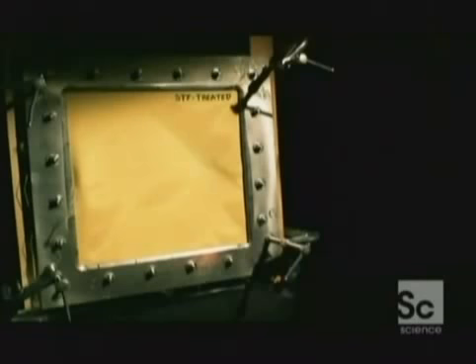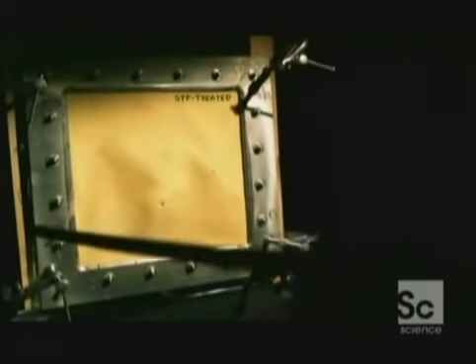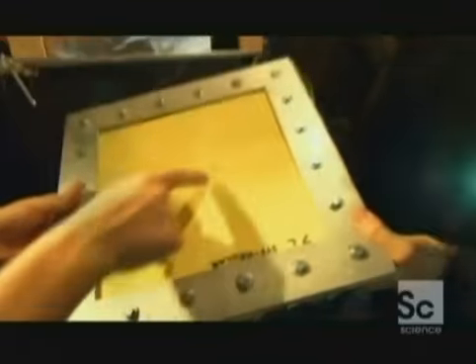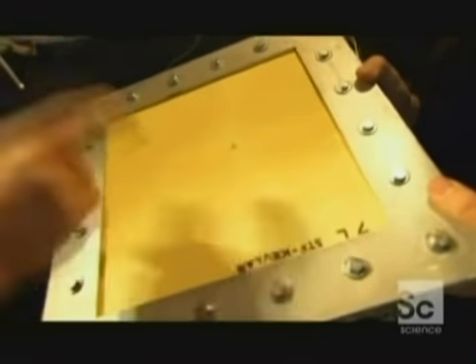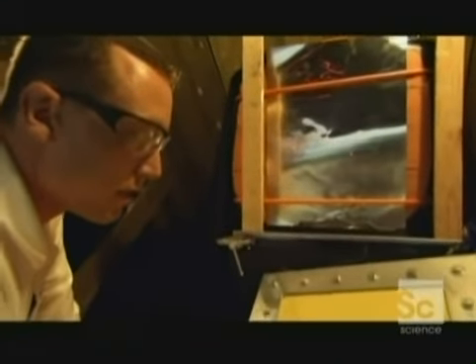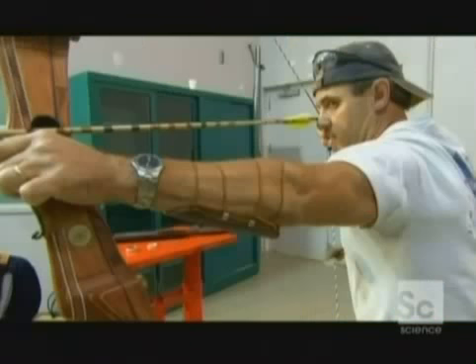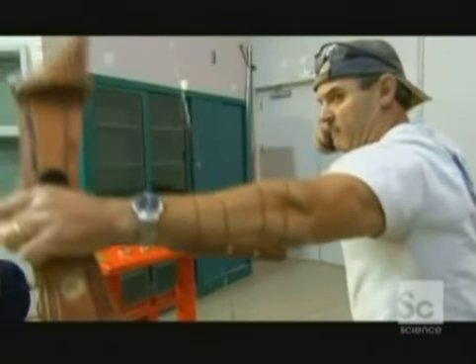Our high-speed camera reveals something incredible. The arrow bounces right off. Ah, here it is. On the floor, not in there at all. Right. So probably what happens, that tip of the arrow, remember it's pointy, started to poke through, but just couldn't find its way all the way through, bounced off and came back. In this case, the shear thickening fluid is holding those fibers in place, won't allow them to slide out of the way, keeps the arrow from getting all the way through.